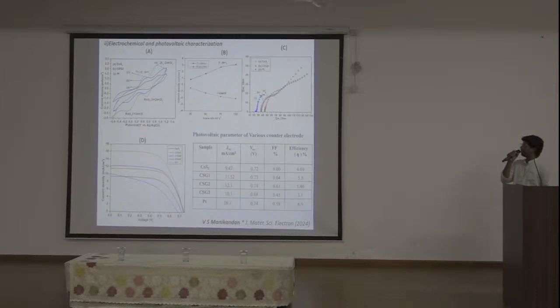After that, the electrochemical impedance spectra. Normally the Nyquist plot shows a semicircle that indicates the charge transfer resistance, showing the different interfacial processes in this DSSC, like the electrolyte and electrode, and the photoanode and counter electrode interface. Moreover, after inclusion of cobalt sulfide in RGO, that is increasing the electrocatalytic activities, and the semicircle arc implies the charge transfer resistance. Here we can see that the series resistance of the cobalt sulfide is reducing after inclusion of RGO. It indicates high electron transportation.